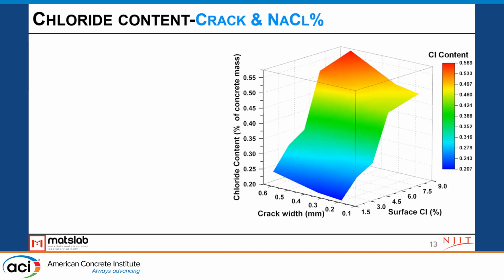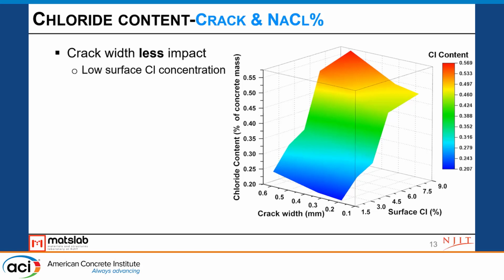If we plot all this series of different chloride concentrations and crack widths in the same graph here, we can see, for example, if we look at a specific surface chloride concentration, at 1.5% surface chloride concentration, the slope we get is relatively small. However, with other concentrations, for example, the 9% one, it is much bigger. So this means the crack width actually has less impact when the surface chloride concentration is low.